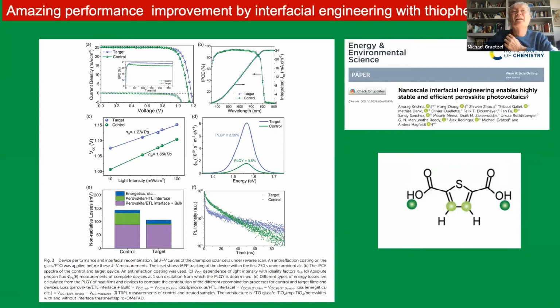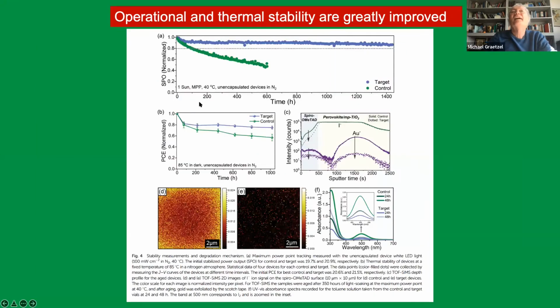That's a lot, and it tells you that you would get a lot more voltage out with a passivator, and you do. You can see the voltage goes up here. It looks like a small increase, but this is all extremely important. And so, yeah, also the stability here, we have 1500 hours. I mean, this is the full solar light on it, and at maximum power point.